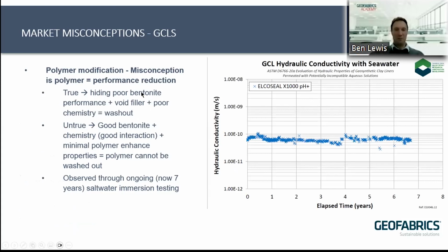I think the perception with polymer modification is that it hides the performance of the bentonite. And in some cases it does, and you'll see that through some GCLs having 20 to 40% polymer added. But we only add 1 to 2%, and it binds very well, so it really only enhances the performance of the bentonite.